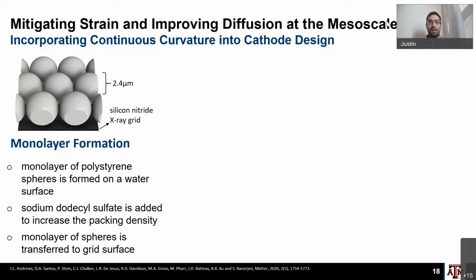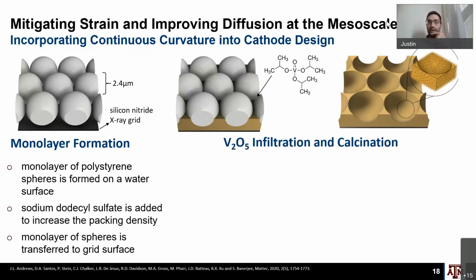We then infiltrate this with an organometallic reagent and do a sol-gel reaction to make a V2O5 matrix. Then we calcine this to both crystallize the V2O5 matrix and burn off the polystyrene. What this leaves us with is an inverse opal pattern. These are common in optics applications, slightly less so in energy storage, but they give us continuous curvature. In the same way that curvature in nanowires impacts lithiation patterns, we were curious how continuous curvature would do that as well.